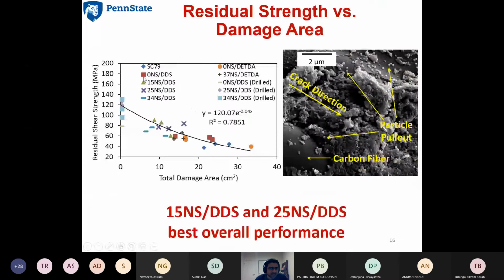In the whole wealth of data that we generated, it took a couple of years to get to this point, but it could be summed up in this one graph, where you see that the total damage area is on the x-axis, and the residual shear strength is on the vertical axis. The residual shear strength is the strength of these tubes after a ballistic impact. And you can see that as the damage area is increasing, the strength of the material is going down.